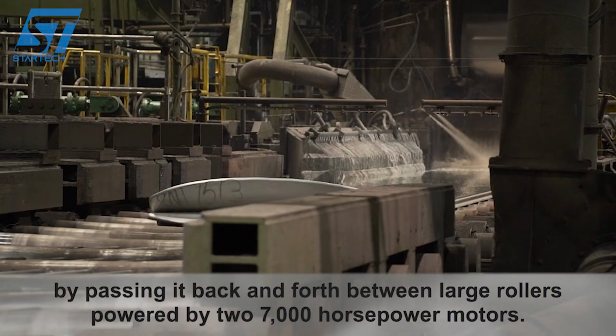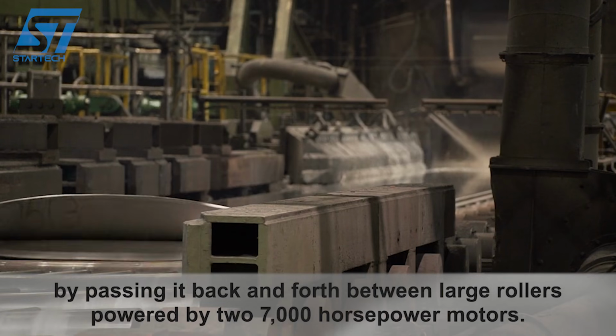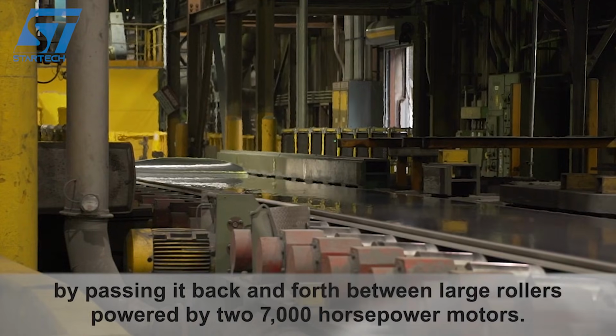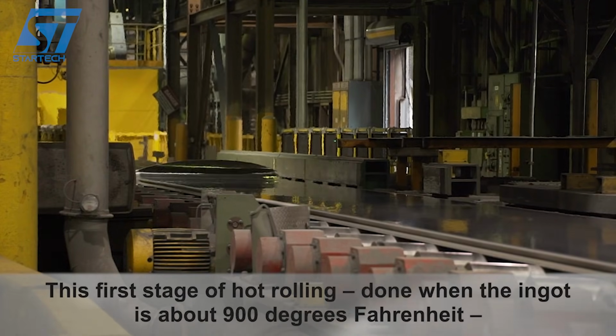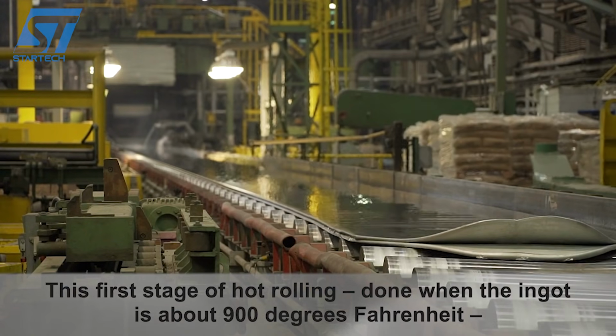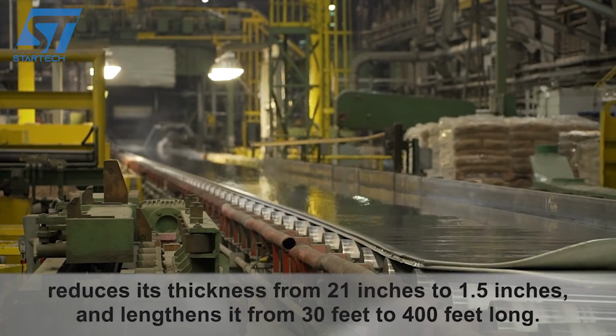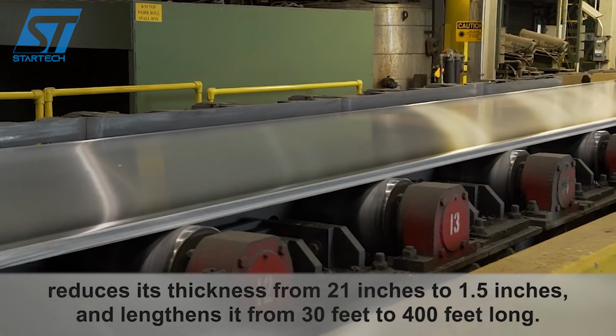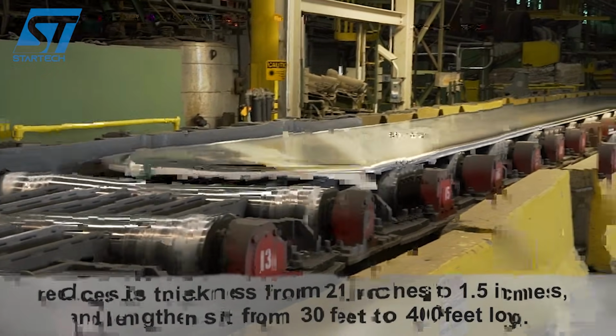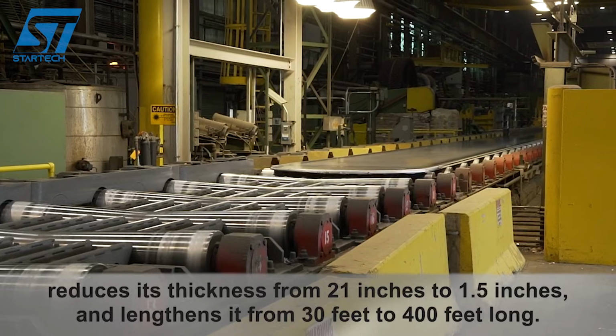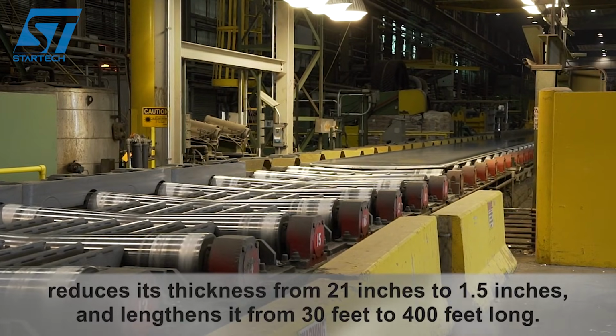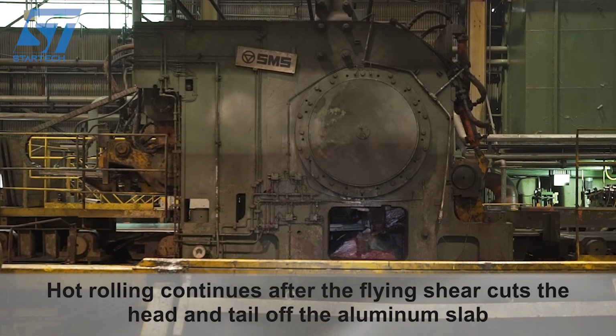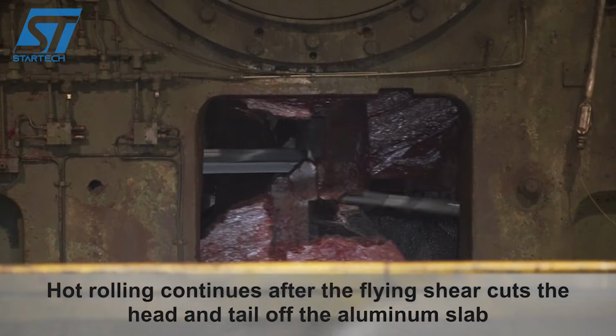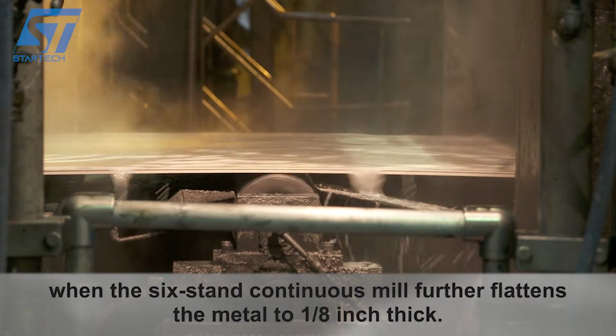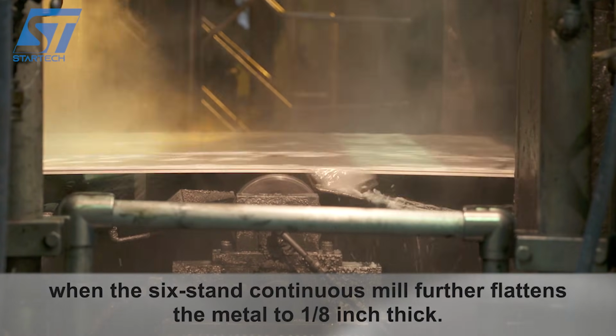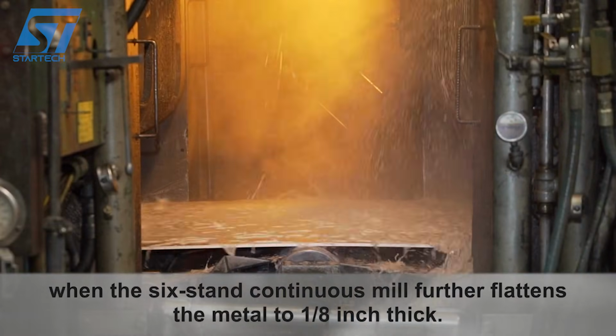The process begins with hot rolling. Those enormous ingots are fed into a reversing hot mill, where the rolls, under enormous pressure, squeeze the aluminum back and forth, gradually reducing its thickness from over 30 inches down to about 1 inch. The aluminum is still very hot at this stage, which makes it malleable and easier to work. The hot mill at Warwick can exert rolling forces exceeding 5,000 tons, and the ingot gets longer with every pass, like rolling out pie dough, only on an industrial scale.